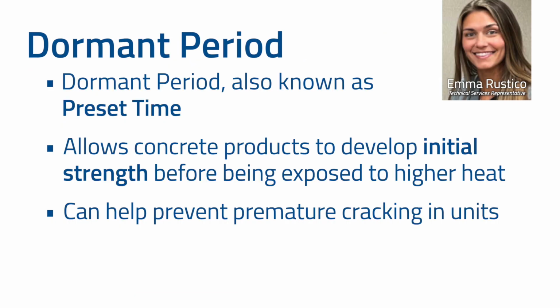The dormant period is the foundation of hydration and is critical for strength development. It can make or break the unit. That is why it has been very important to not crank up the heat as soon as the units go into the curing chamber. If the heat is applied too soon, the units will crack due to insufficient strength. What this means for production is that there are parts of the curing process that cannot be skipped or rushed.